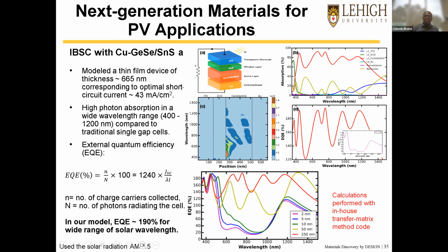So it is a confirmatory experiment that shows that these computationally synthesized materials could indeed be made in the lab in an experimental setting. We also went a step further to see if we can learn anything about their potential application as photovoltaic systems. So what we did is we constructed a solar cell array where we use our new material as an active layer. What I'm showing here is the photocurrent generation, and this is the absorption of the various layers, and this is the optimized external quantum efficiency of our material.